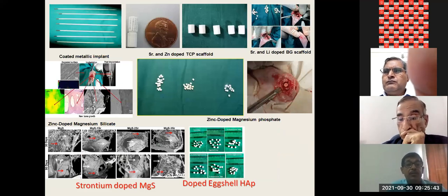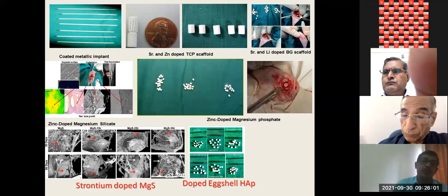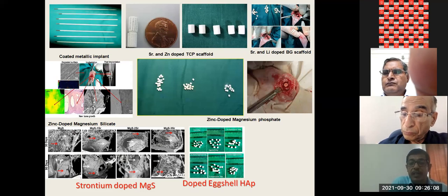Later on, in human and animal surgery, we commonly use stainless steel material for fracture fixation devices. But the problem with stainless steel or any metallic material is the leaching of metallic ions, which leads to metallosis. To overcome that situation, we coated the implants with ceramic to prevent this leaching. Later we did trials in animal and human models also, in collaboration with RGKR Medical College, and we saw that the leaching phenomenon is very low.